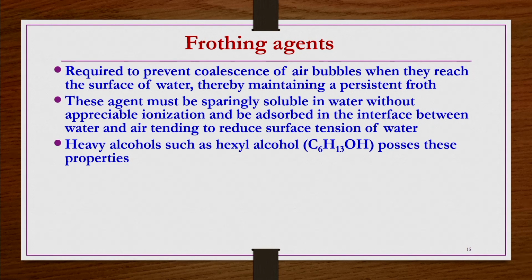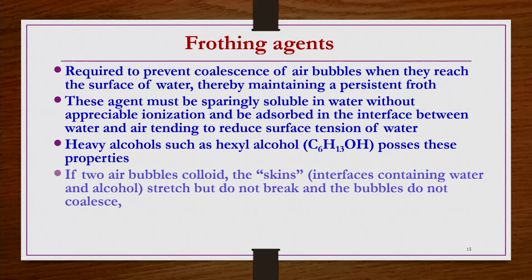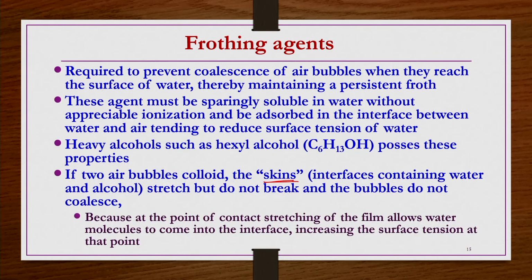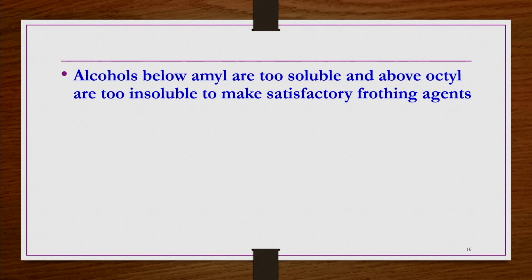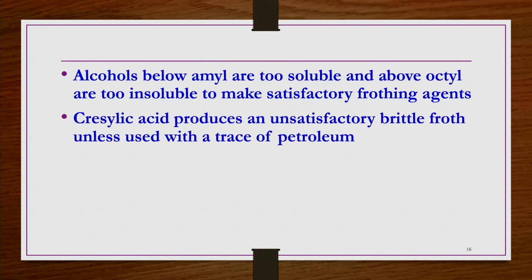Heavy alcohols such as hexyl alcohol possess these properties. If two air bubbles collide, the skins, the interface containing the water and alcohol, stretch but do not break, and then the bubbles do not coalesce. That is the purpose of these frothing agents. Because at the point of contact, stretching of the film allows water molecules to come into the interface, increasing the surface tension at that point. Alcohols below amyl are too soluble and above octyl are too insoluble to make satisfactory frothing agents. So, one should be careful about these alcohols.